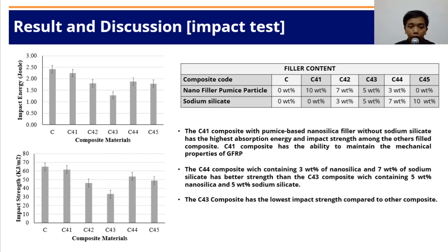From the following chart, it can be seen that the C44 composite containing 3% nanosilica and 7% sodium silicate has better strength than the C43 composite containing 5% nanosilica and 5% sodium silicate. This phenomenon is due to the role of sodium silicate in the distribution of homogeneous particles, which can help to minimize porosity. The C43 composite has the lowest impact strength compared to the other composites.